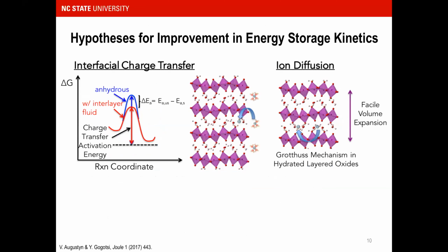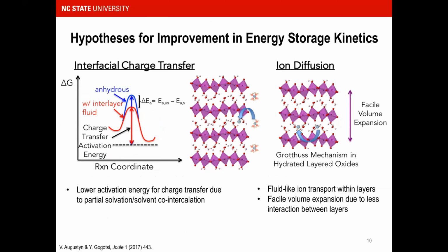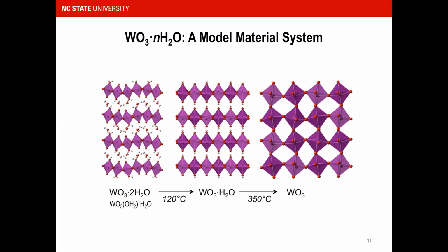So we had these hypotheses that we could decrease the interfacial charge transfer that occurs in the electrochemical reaction, and we could perhaps also have much faster ion diffusion through mechanisms that are more fluid-like, or simply faster cell volume expansion because you have lower density structures. And so what our group's been doing is we've taken a look at this model material system based on tungsten oxide hydrates. These are thermodynamically stable materials that you can readily synthesize at room temperature from a sodium tungstate salt.